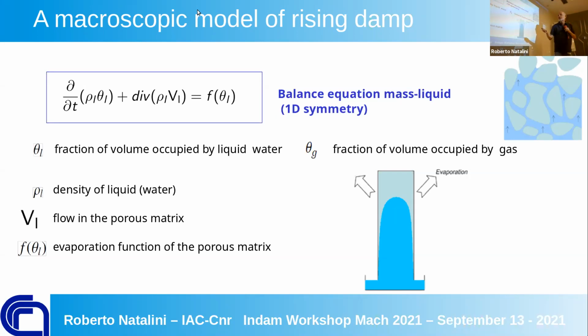And the V is the flow in the porous matrix. So it's some sort of measure of what is passing, really, the quantity of material passing inside the pore per unit of time. And then we have a term which is evaporation, which we are not speaking about, but usually when you have a real brick, a real wall, you have to consider that there are some surfaces where you have evaporation, so you have to take it into account in your equation.